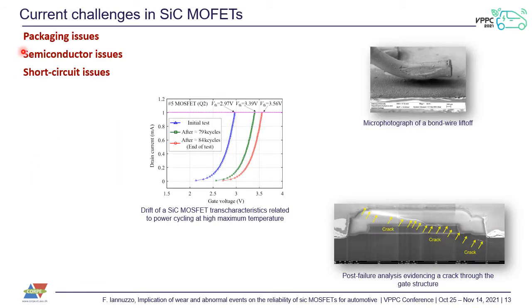By packaging issues, I mean something which is related to the packaging itself. In this case, for example, we have a typical bond wire liftoff, which turns out to be very critical in silicon carbide applications. By semiconductor issues, I mean something which is affecting the semiconductor itself, typically with a parametric drift or something like this. And finally, by short circuit issues, I'm referring to something which is happening in connection with short circuit events, like in this picture here, where I show a post-failure analysis result after a short circuit test evidencing a crack through the gate structure.